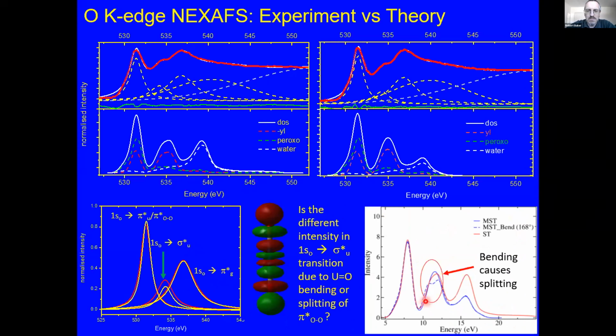But what gives us the best clue is actually if we take our bent metastudtite and plot the density of states, and you can see that it starts to split. So we think now that what we have here is evidence for a bend in the uranyl bond. So this is really clear. I think this is our interpretation of our data, that dehydration, so removing that water of crystallization, actually bends the